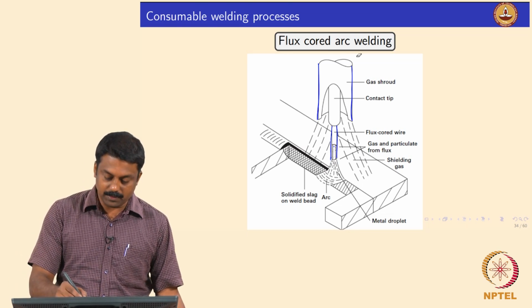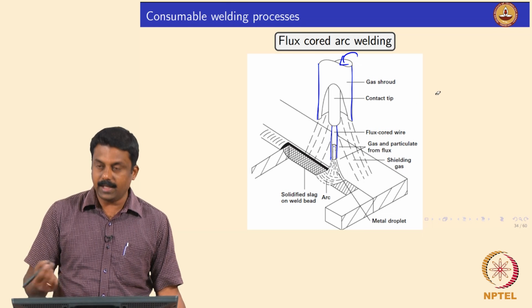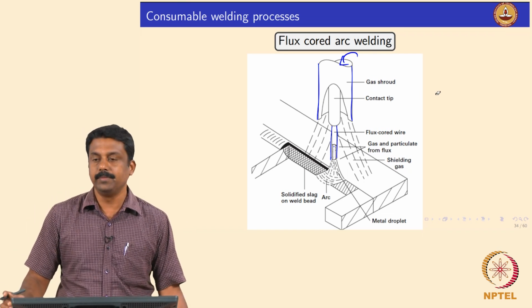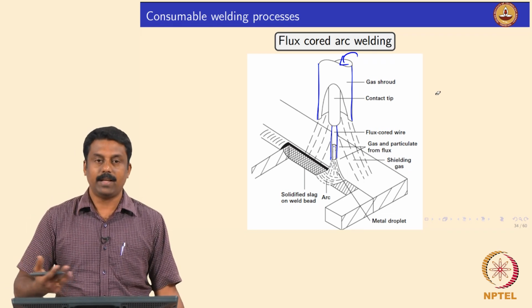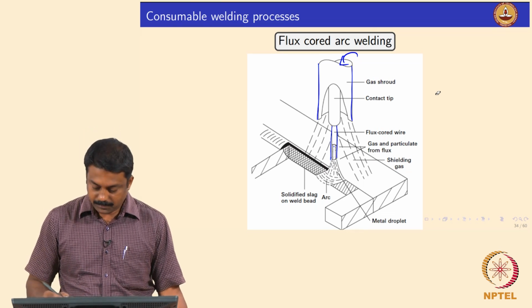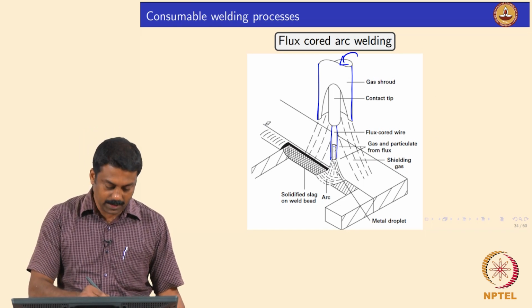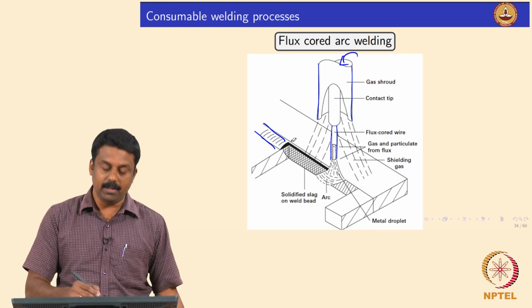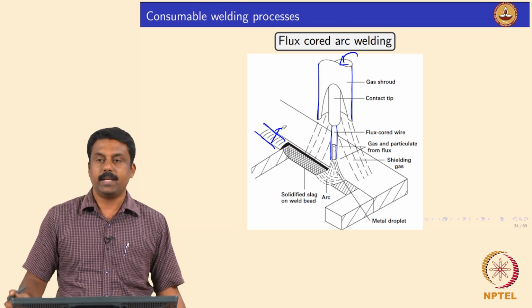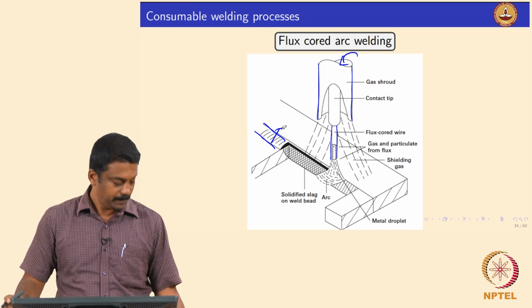So, sometimes you may also send the shielding gas, and if you are using a self shielded FCAW, you do not need shielding gas, because flux itself can generate shielding gas, right. It is clear. So, then you have a slag deposited on top of the weld pool, and then you can break it after welding. Good.